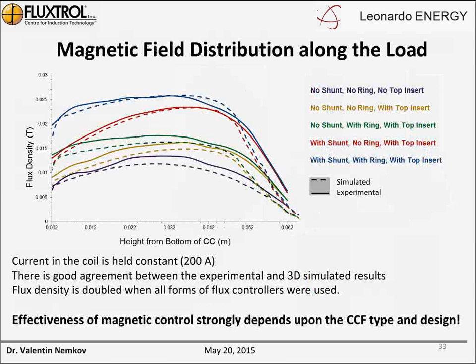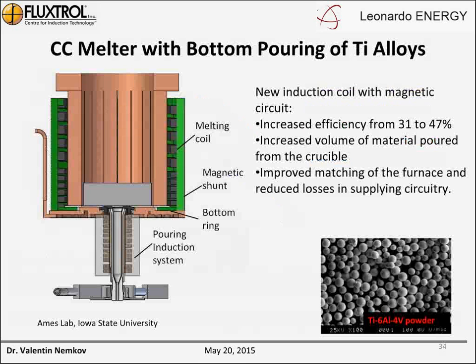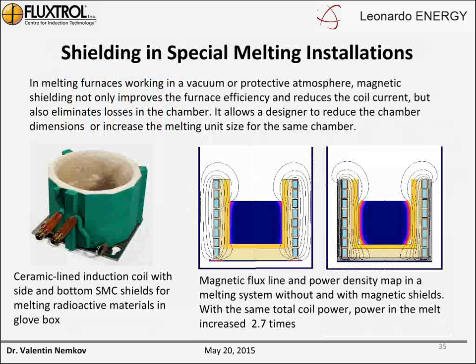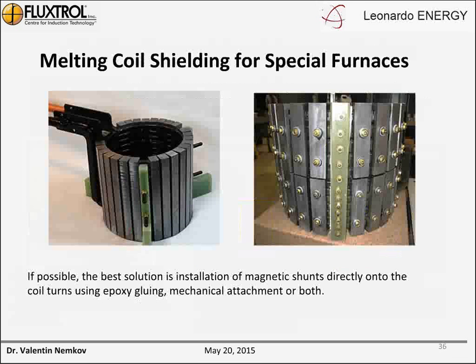The other parameter which is very essential for cold crucible melting is the distribution of power along the melt. These results were confirmed by industrial application. Here you can see the real working installation, a CC melter for bottom pouring of titanium alloys. Now, I want to show you some slides about the special melting installations.